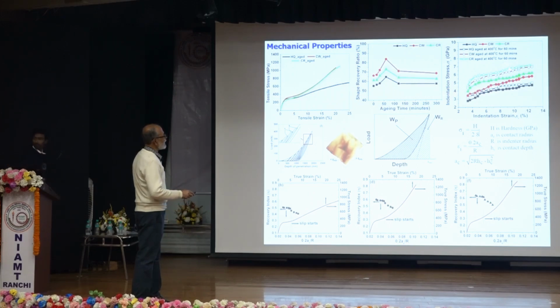You can see the as-received samples, which are open circles. See, red one is cold worked, black is homogenized and quenched, and green is cryo-rolled. So when you age them, in all the cases, you have seen that there is certain hardening, right? So we have seen the nanoindentation curve for each cycle. For each cycle, you can see we need a bit of higher load for initiation of plastic deformation. So there is this example.